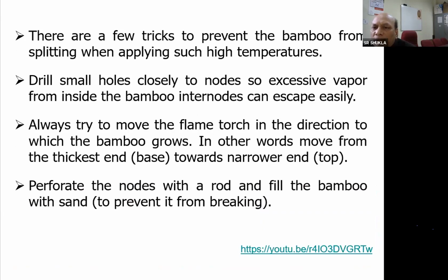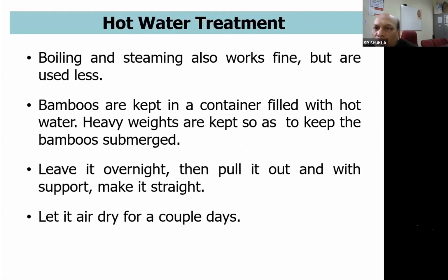And we have to always try to move the flame torch in the direction in which the bamboo grows, like from bottom to the top direction, from thickest end to the narrower end, so that these cracks and charring will not take place. And then we perforated the node with the small rod and fill the bamboo with sand. That will also prevent the breaking of the bamboos.